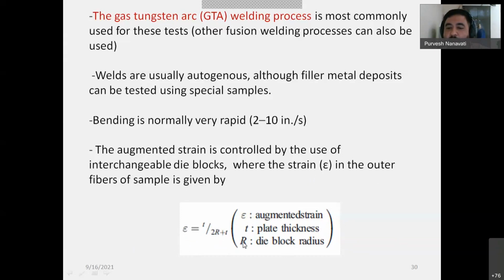So now you go on changing the die block, obviously, because for your plate thickness, you can qualify different plate thicknesses, because most of the time your qualification for various tests will start from more than 3 mm thickness. I'll come to this: what are the thickness limitations, and how can we go for other tests for thin plate qualification, right? But most of the time you can start with 3 mm thick and more, and this R is the die block radius. So you can vary the die block radius, and since it is in the denominator, the strain will be inversely proportional to it. So the smaller the die block radius you take, the more strain will be produced, right? It is a simple formula. Okay.